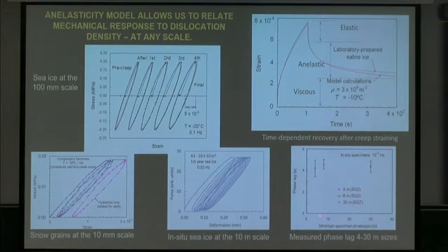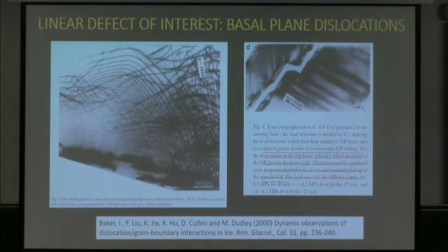We've done some scale effects, still work in progress on the fracture side, but on the constitutive side, I'm happy to report we really don't see much in the way of scale effects on the constitutive behavior. And that's going from 4 to 30 meter square samples. So that's good news. A little exercise with the model just showing how it picks up primary creep. I'll be talking about this anelastic component, which is time dependent and recoverable. Viscous is the permanent strain that never comes back.